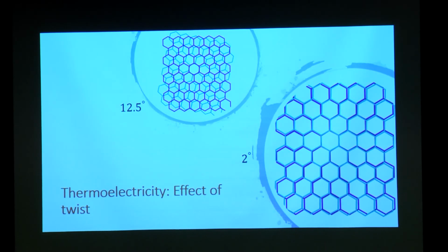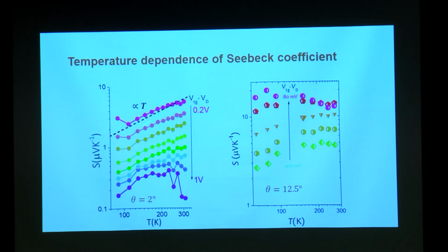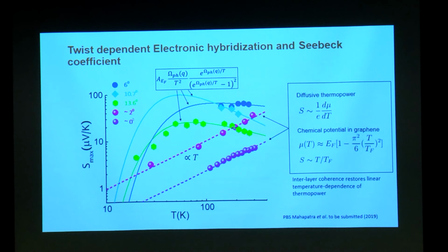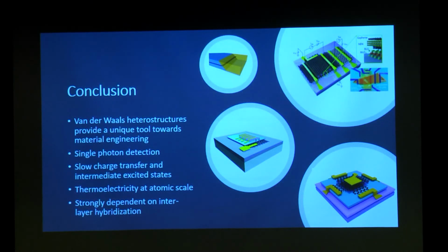And if you go to a lower angle where the two are strongly coupled, you can see this is highly Mott type. You can get the Mott relation back when you change the hybridization by changing the angle between the two layers. Anyway, this is my last slide. You can see, depending on the angle, what happens to the thermoelectric figure of merit as a function of temperature. This is more or less the summary.